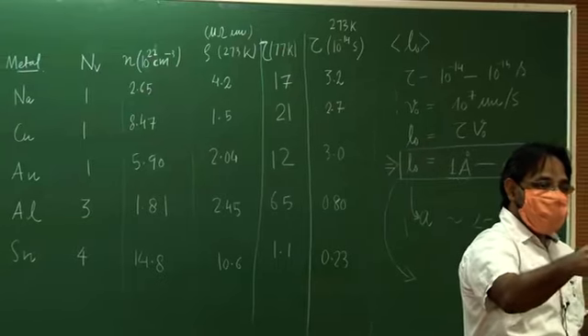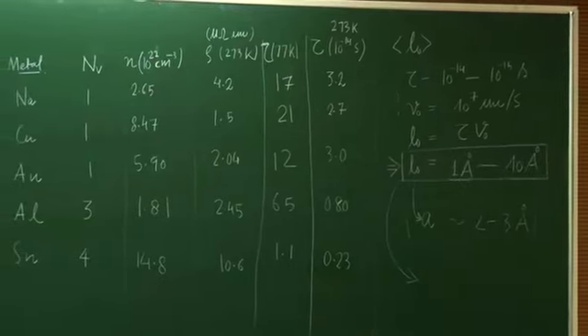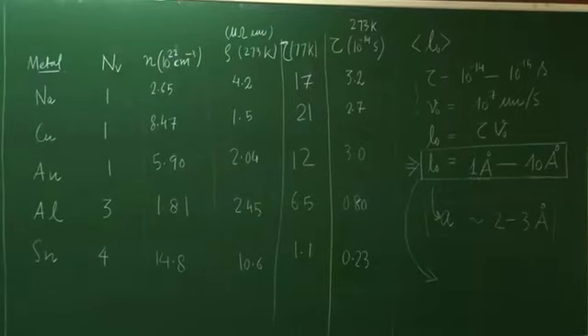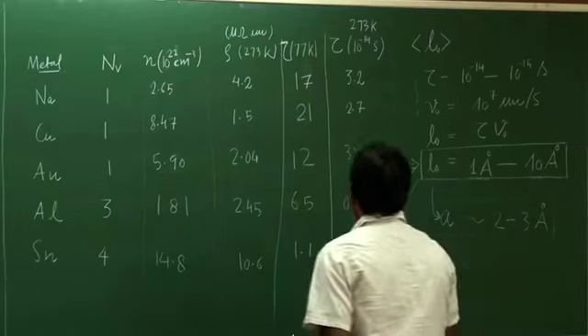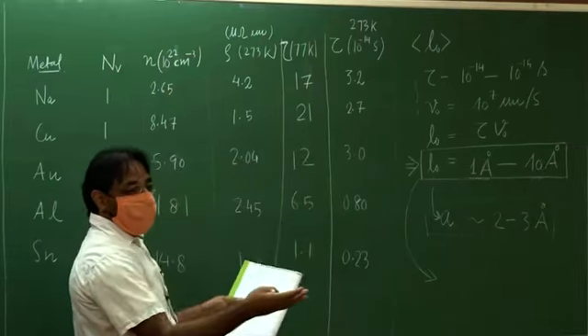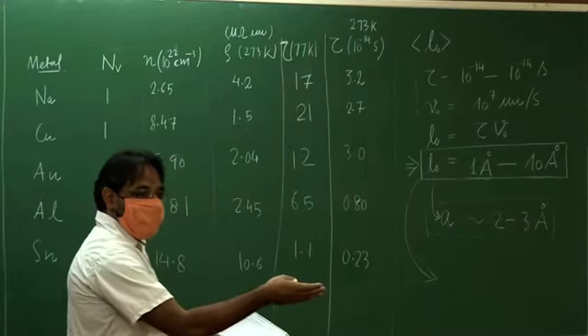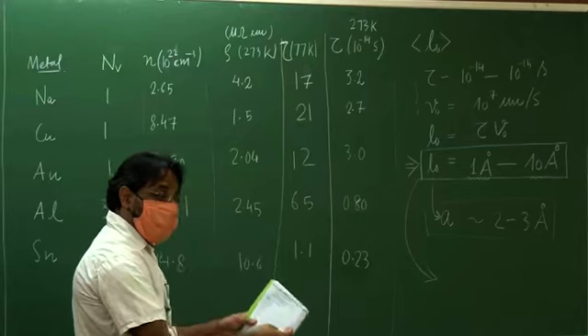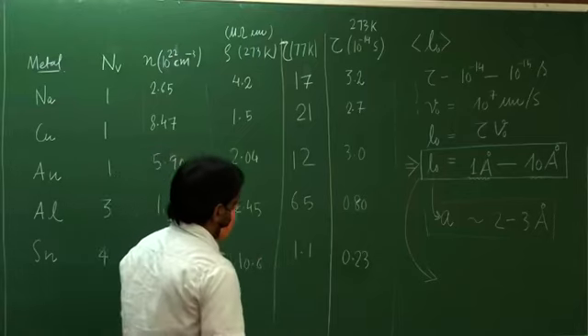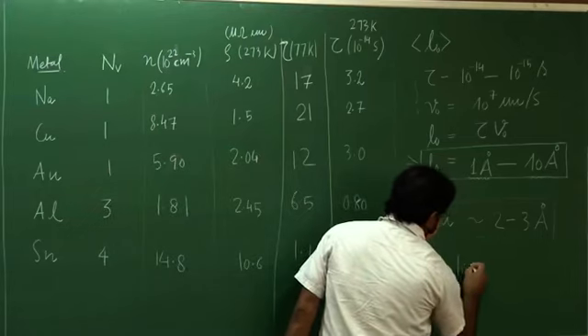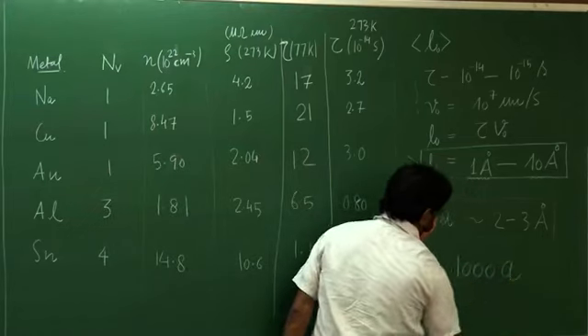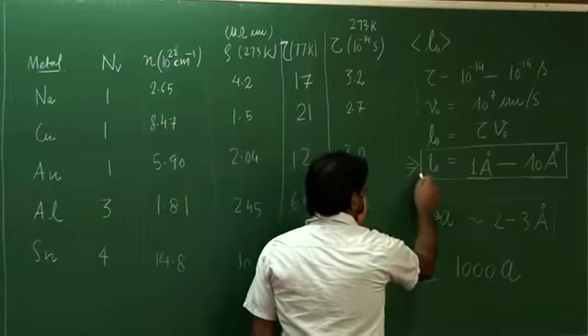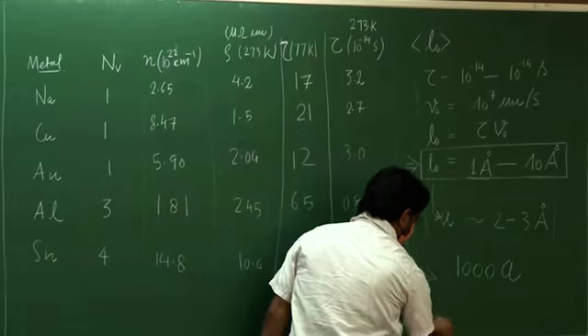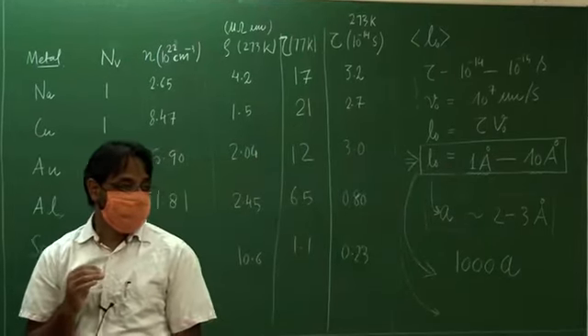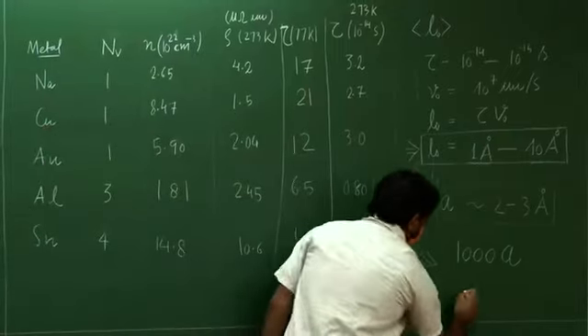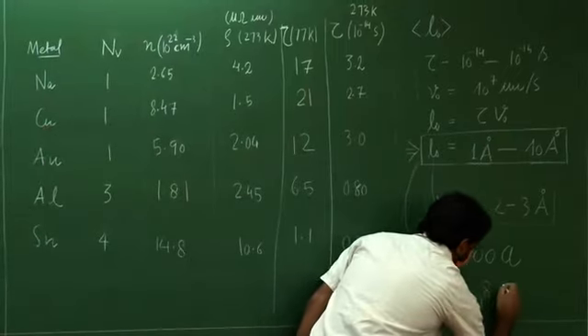approximately 1000 lattice spacings. Now this is clearly contradicting Drude's model, because in Drude's model the electron is getting bombarded by the ionic cores every now and then, and there is no reason why it should not collide with an ionic core if it is there. So electrons somehow can bypass these ionic cores and travel as far as 1000 lattice spacings. In fact, if you go to even lower temperatures and prepare your material very carefully, then this can be as large as 10 to the power 8 lattice spacings.